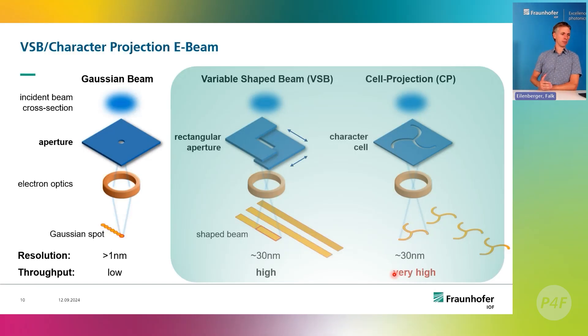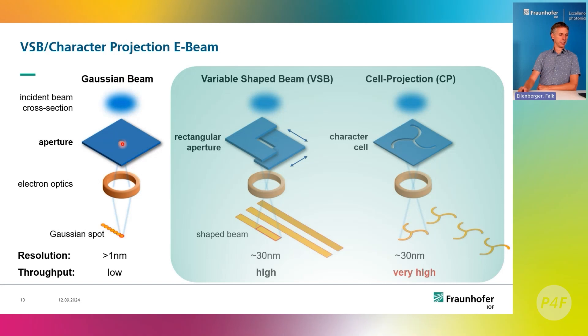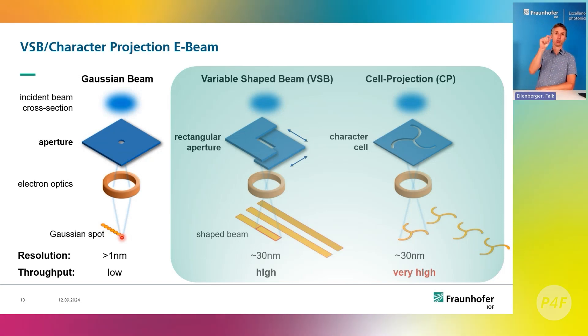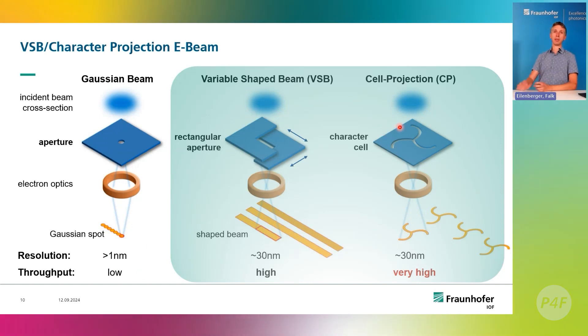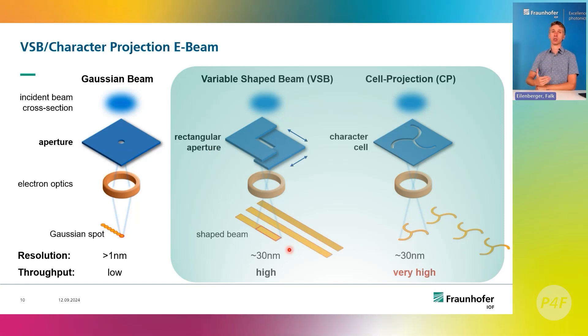What do variable shape beam and cell projection modes mean? In a normal electron beam writing machine, a circular aperture is imaged onto the substrate to expose a photoresist. This gives high resolution but you have to write large structures from a small pencil, which takes a long time. The variable shape beam mode lets us write little squares or rectangles of arbitrary shape instead of a single point — which is particularly interesting for one-dimensional nanostructures, also called optical gratings.